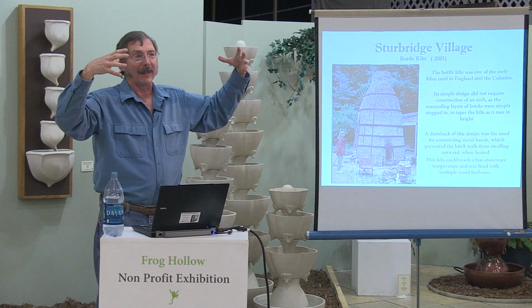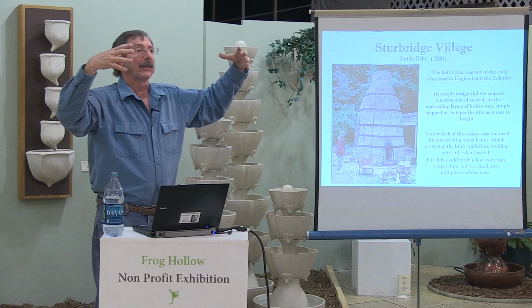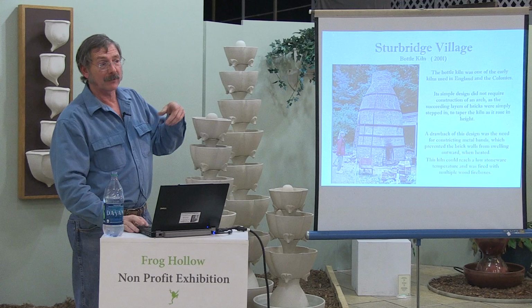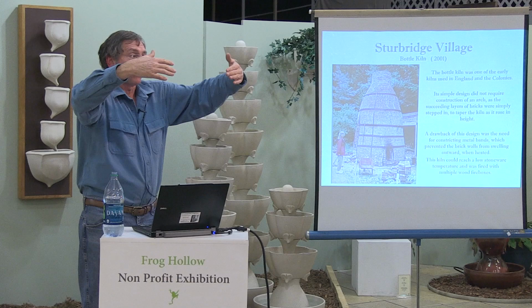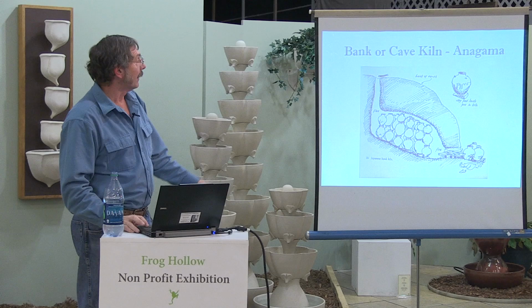If you can expand out to a certain point and then cool, it'll come back a little bit. But if it keeps expanding out, the whole thing is going to collapse. So you have to have metal bands around that. And you'll see the same thing on those salt kilns I showed earlier. They all had metal bands holding that dome in place. Without that, all the thrust was going to be going outward. So this is the first or the earliest form of high fire kiln.